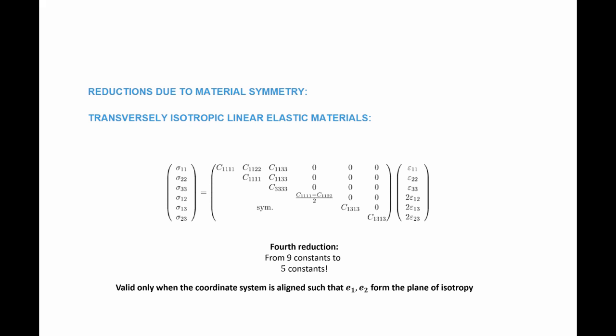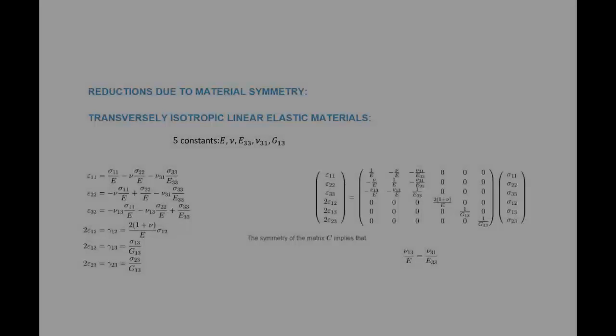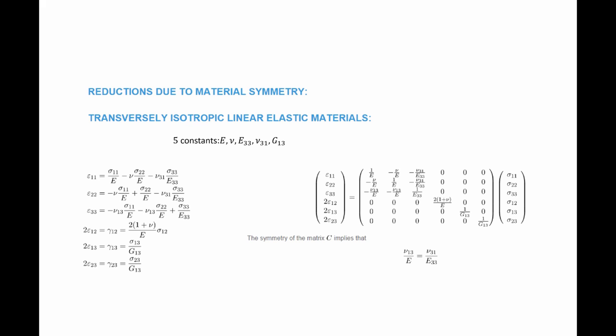Similar to the orthotropic material, this matrix of properties is valid only in the coordinate system where e_1 and e_2 are aligned with the plane of isotropy. We can choose 5 constants with specific physical meaning. Young's modulus E and Poisson's ratio nu describe the response in the plane of isotropy. E_33 describes the ratio of axial stress to axial strain perpendicular to the plane of isotropy. Poisson's ratio nu_31 describes the ratio of the strain in the plane of isotropy to the strain in the perpendicular direction. G_13 describes the relationship between shear stress and shear strain out of the plane of isotropy.